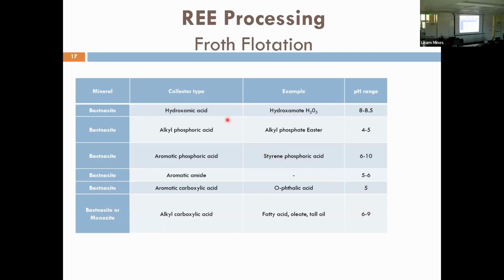In this table, you will have different types of collector that are usually applied in the flotation of rare earth. And this is the working pH range for them. Again, the working pH range is very important to think about when you design your flotation for any mineral concentration process, because there are specific pH values. Outside that range, there will be limited interaction between the collector and mineral surface. So you have to think about this when designing your flotation circuit for any mineral.